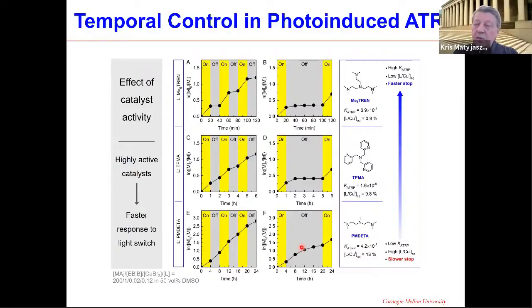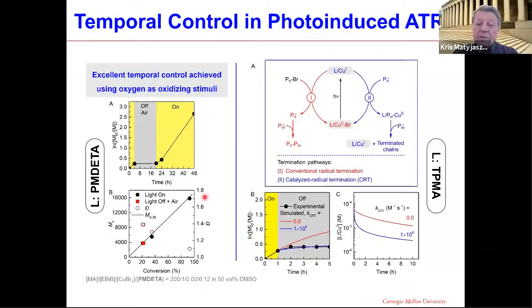So how can we stop this system with PMDETA? Can we just wait for many hours, or can we do something to stop it in the dark? In fact, the easiest way is to expose it to oxygen. After opening to air, the reaction stops nearly completely because all of this copper 1 gets oxidized to copper 2. And then you can regenerate it if you wish.